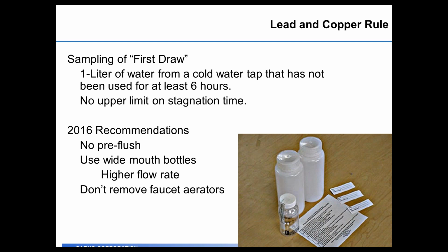In 2016, after the issues with Flint, the US EPA sent out a recommendation update and recommended several things that utilities must not do when they work with customers. At that time, they recommended that you not recommend a pre-flush to the consumer, which means the night before the sample is pulled, you should not recommend that the consumer flush their water line for 5 to 10 minutes prior to shutting it off before starting the test.